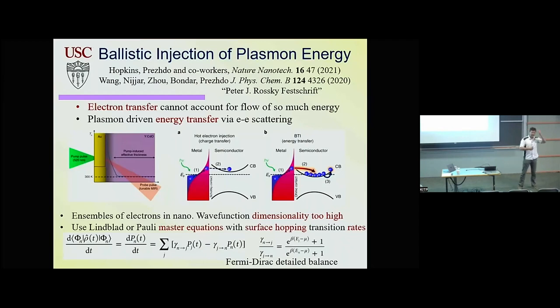the other way. So in this experiment, what they've done, they put a metal film, and then they have a semiconductor, and then now they also have another metal here, and they're able to conduct heat one way and not the other way. So what happens in this case is that you have a metallic system where you excite electrons, and these electrons scatter with electrons in the semiconductor. So the semiconductor is intrinsically doped. It has some electrons in the conduction band. And instead of charge transfer, you actually have energy transfer.